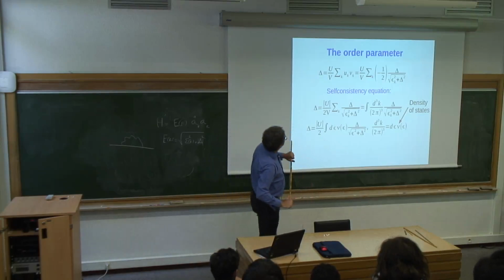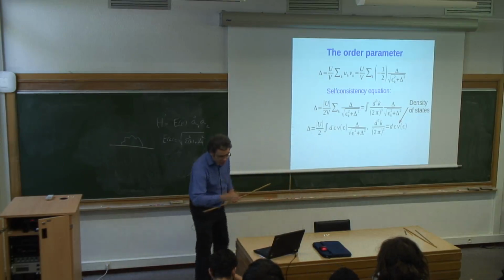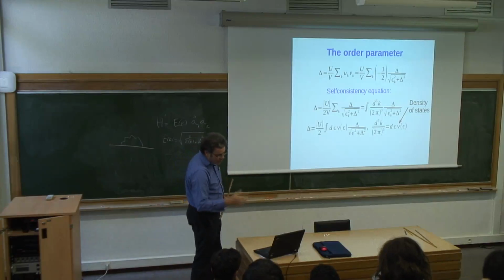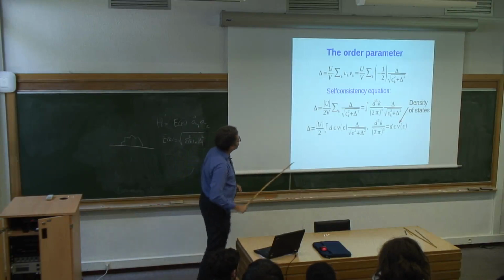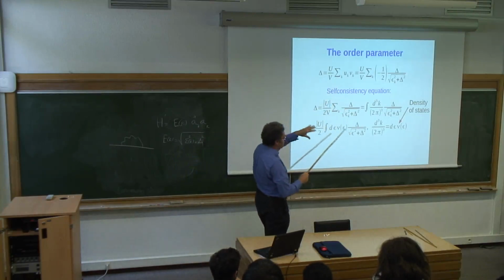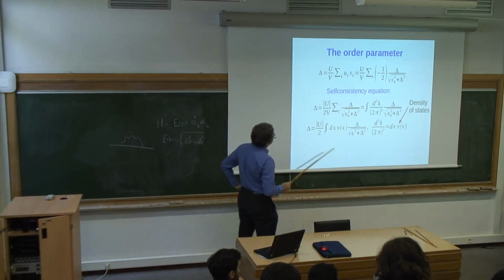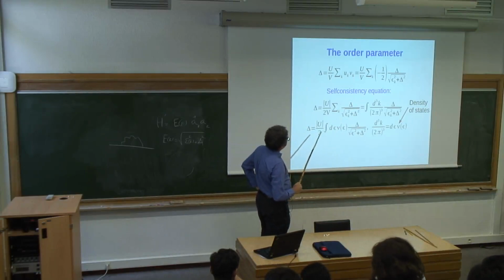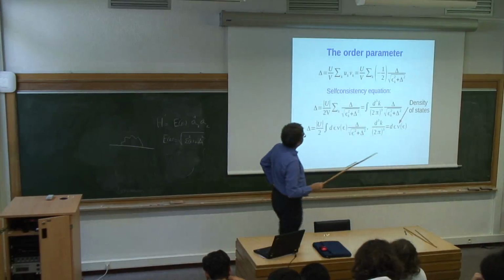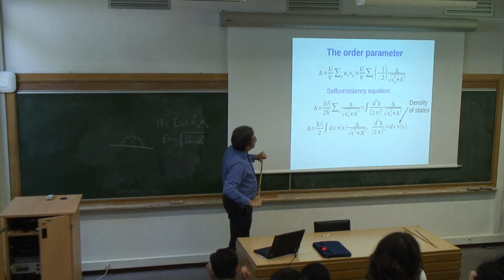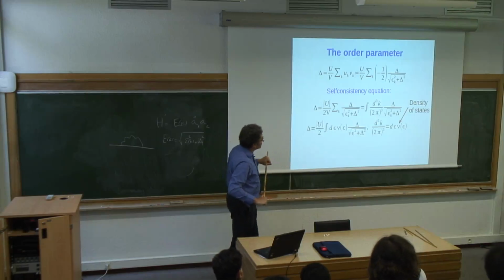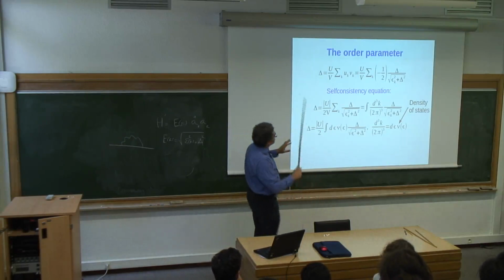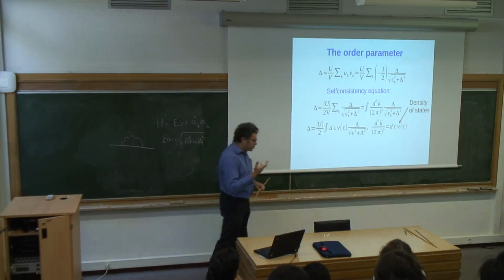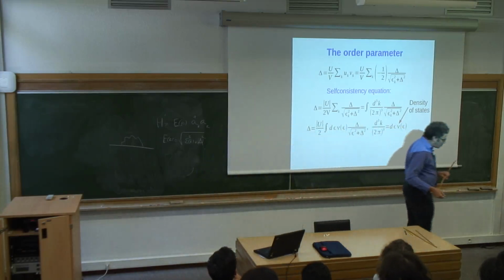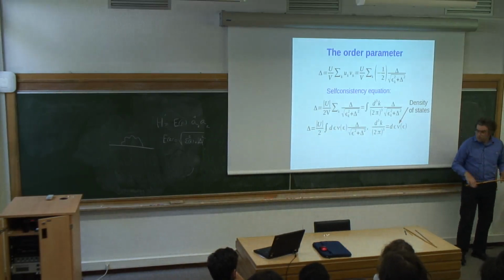So then the last thing we want to do is to write down the self-consistency equation for the superconducting gap. If you take the formula by which it was defined and then take the expectation value of all operators and express them through the coefficients of this canonical transformation that we introduced, then you get this, and that gives you a self-consistency equation that determines the order parameter. Depending on your interactions and also on temperature, which you can put in these equations, it can be zero or non-zero. And so this equation plays the same role as the self-consistency equation by which you predict whether your ferromagnet is in a paramagnetic state or in a ferromagnetic state.